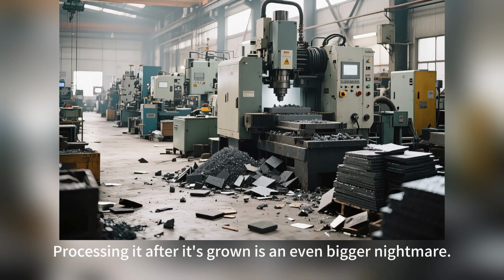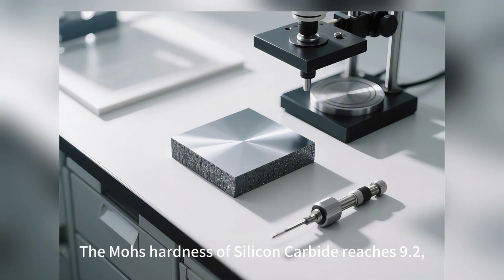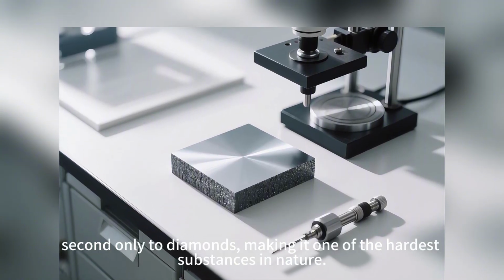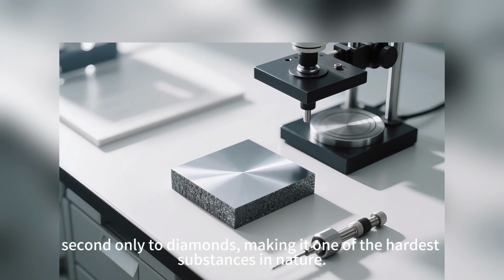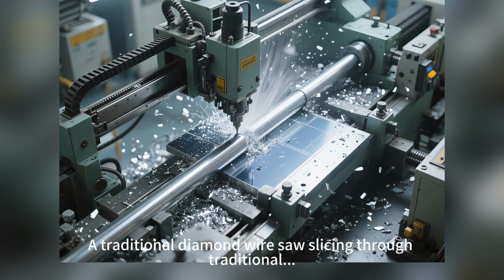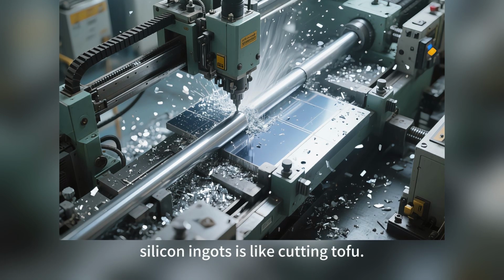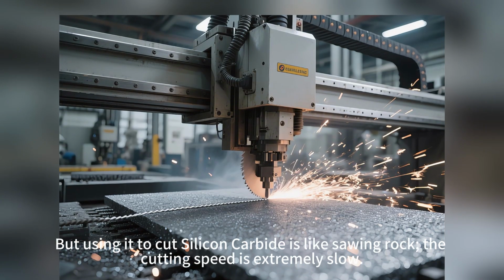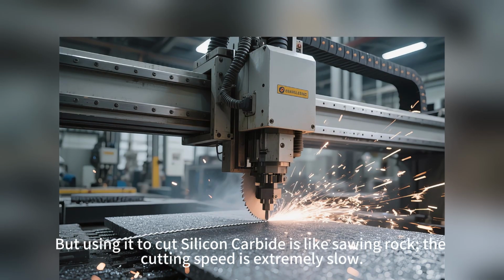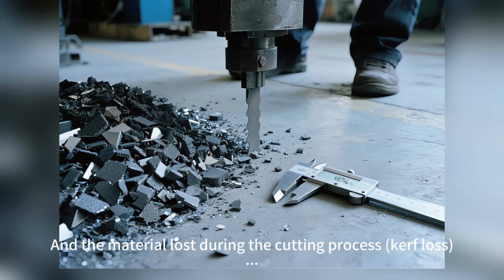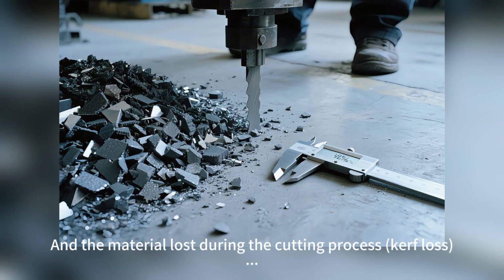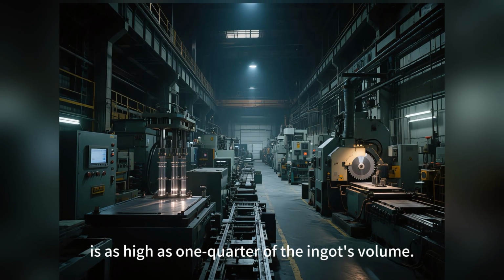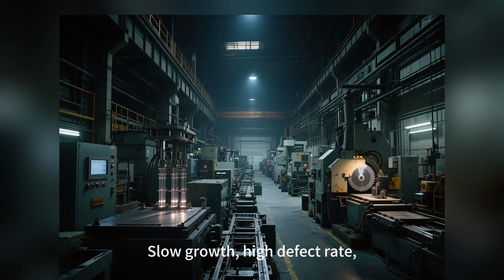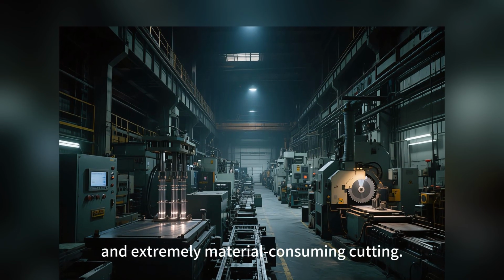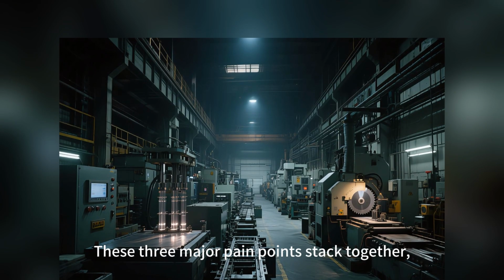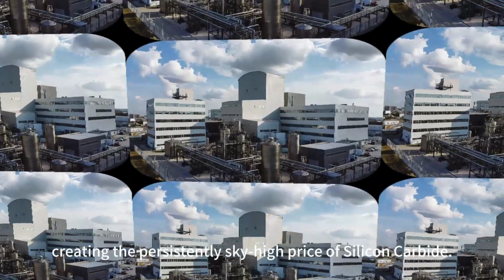Processing it after it's grown is an even bigger nightmare. The Mohs hardness of silicon carbide reaches 9.2, second only to diamonds, making it one of the hardest substances in nature. A traditional diamond wire saw slicing through traditional silicon ingots is like cutting tofu. But using it to cut silicon carbide is like sawing rock. The cutting speed is extremely slow, and the material lost during the cutting process, kerf loss, is as high as 1/4 of the ingot's volume. Slow growth, high defect rate, and extremely material-consuming cutting. These 3 major pain points stack together, creating the persistently sky-high price of silicon carbide.